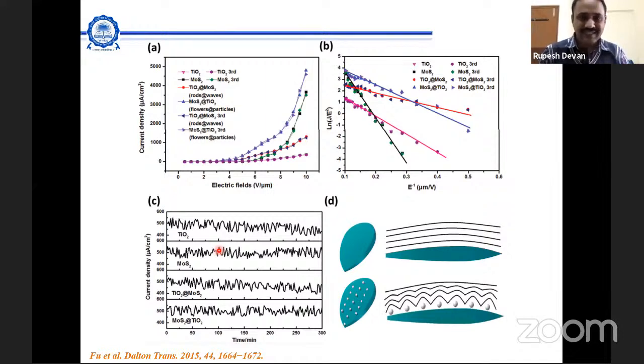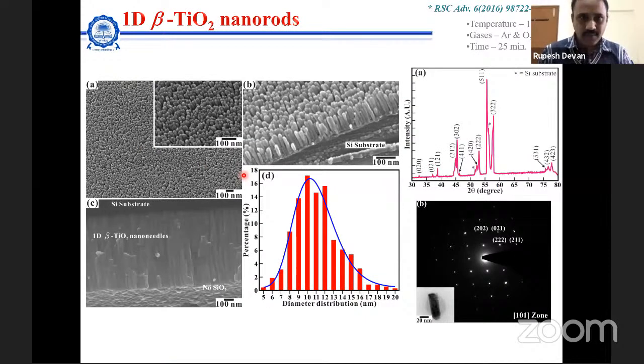So we thought, let's take this challenge, but not go with the rutile structure; go with the brookite structure. Brookite is a metastable phase, which is quite difficult to synthesize, but we have done it in our laboratory. You can see these rods are vertically aligned, and all lie between 5 to 20 nanometer, but most of the rods have a diameter around 10 nanometer. Then we confirmed this brookite structure using TEM and XRD.